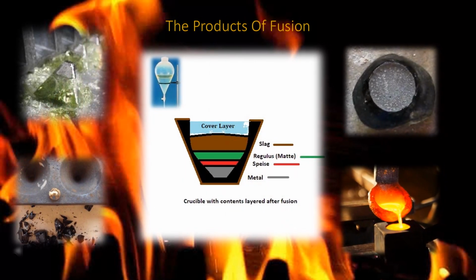During fusion, the solid material melts. In essence, this molten material can be considered as a solution. The solutions will separate into layers, with the densest solution forming at the bottom and the lighter solutions forming above. The contents of the crucible can be likened to the solutions sitting in a separatory flask. When cooled, the solutions will solidify, resulting in different layers. Starting with the bottom layer will be the solidified lead button containing the gold, silver, and the platinum group metals, if any. This button should be soft, malleable, and shiny in appearance. It should also be easily removed from the glassy slag.